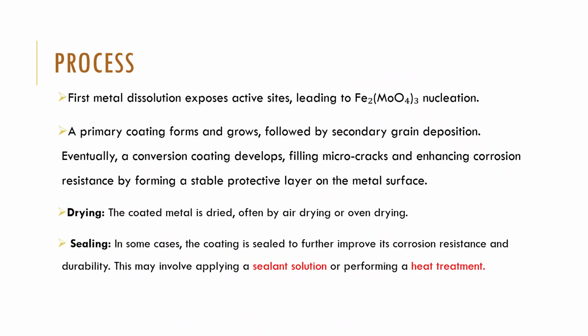So what is the process? Let me summarize. First step is the dissolution of the metal surface. Second step is the primary coating is started forming on the surface. Over that, secondary coating is formed, and now it is removed and it is washed and dried. After drying, if we see micro cracks are there, then we do the process of sealing, right? So sealant solution or heat treatment is given.